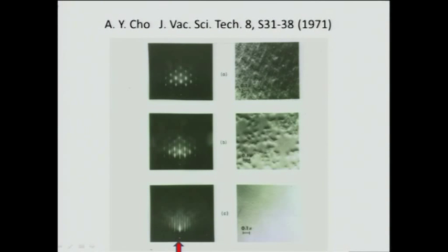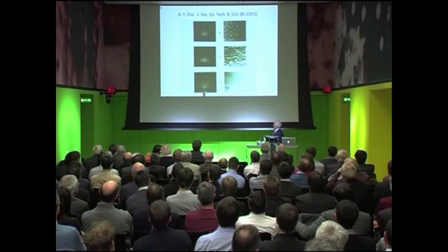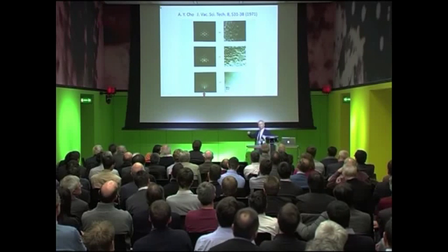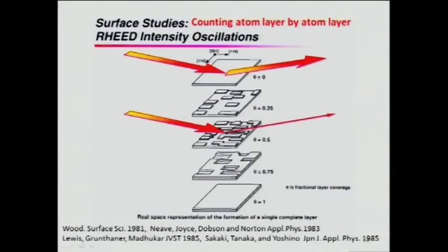I also want to point this out. We have heard MBE is growing atom layer by atom layer. And here I want to demonstrate to you it really is growing atom layer by atom layer. Notice here in the electron diffraction, we have one spot here. This spot is called the specularly reflected electron beam on the surface. Now, we use that to study the surface, counting atom layer by atom layer with reflection high-energy electron diffraction intensity oscillation. The spot I just showed you earlier oscillates in intensity as we grow. And every oscillation means one atom layer is grown.